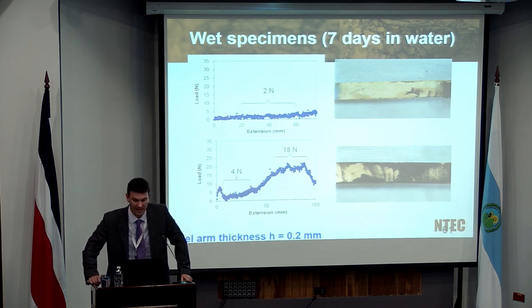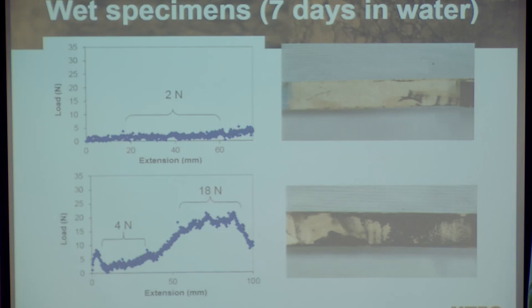But if we look at the next extreme, if we look at what happens after 7 days, we now find that the actual load in our peel test has dropped down to 2 newtons in the top figure. I've included the bottom figure just to show that there is quite a lot of variability now. As you start to damage your specimens, inevitably some will perform better than others. But again, there were portions of that bottom specimen that also had dropped down to about 4 newtons.